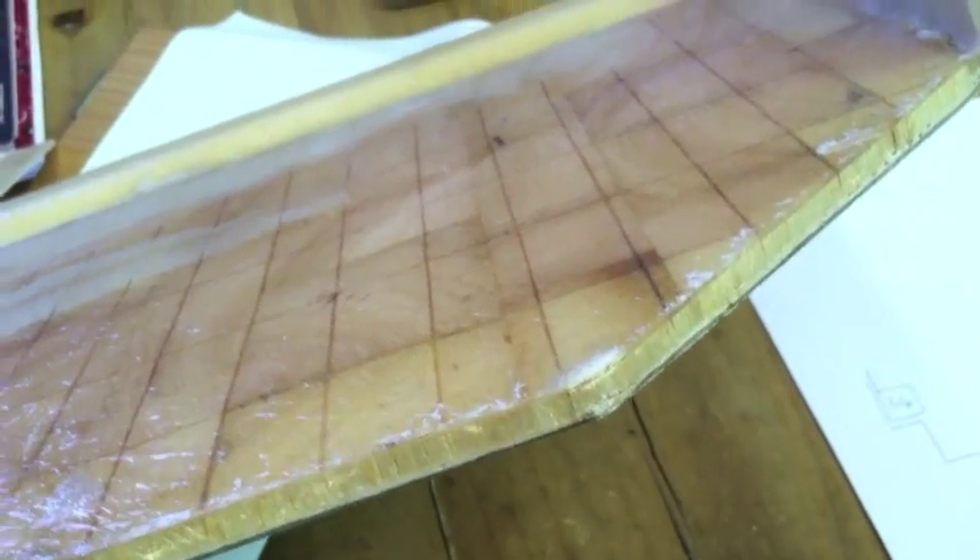As you can see in these walls, everything aligns like it's supposed to. Here's a close-up of our composite wall. The marine-grade gel coat exterior has a UV protectant to it. It has a resin and then a directional fiberglass, a balsa wood core. We use an end-grain light balsa, which uses less resin to set up — that helps keep the weight of the walls down and actually creates even more strength. Fiberglass is interesting because the more porous material you put between the two pieces of fiberglass, the more honeycomb effect you get, and the stronger the fiberglass piece becomes.